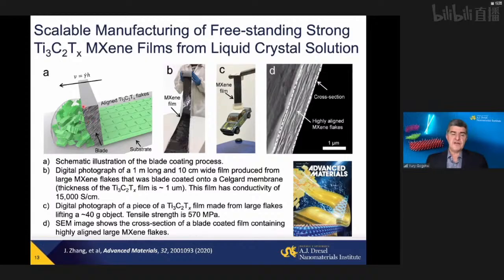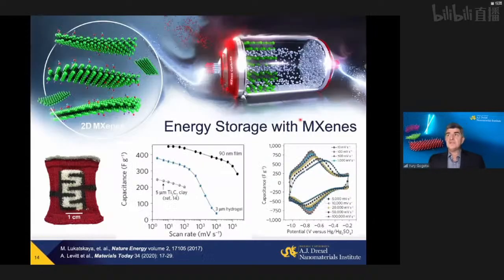You need to add surfactants to carbon nanotubes or graphene to be able to disperse them in water. With MXene, no additives needed, no binder, nothing. Moreover, you can use MXene as a binder. And all this justifies and motivates electrochemical applications of materials in energy storage.